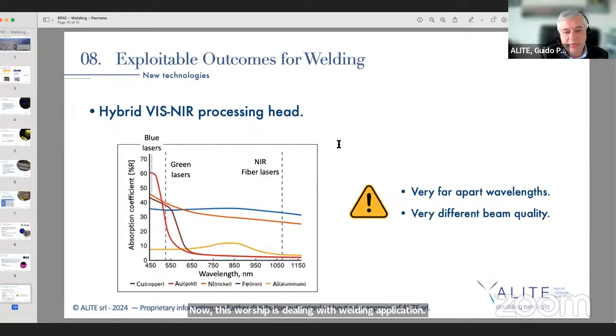Now, this workshop is dealing with welding applications. So how can we use the expertise that we have gained and are gaining in working on special projects for welding? Well, in my opinion, the first thing could be developing hybrid visible, near-infrared processing heads. This is because, as you can see from the graph we have here, it's pretty famous these days, everybody is talking about the processing of highly reflective materials, copper, which is critical for the electrical transition, gold, etc. And as you all know, these materials are not processed very well with near-infrared fiber lasers, so lasers emitting at around 10-something nanometers, for example 1050, 1070 nanometers.